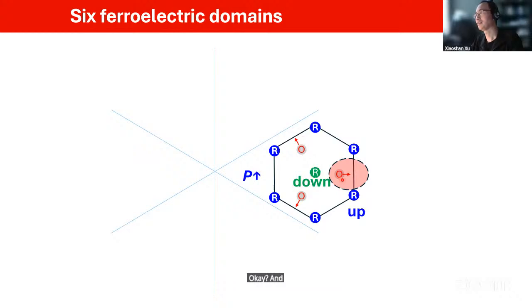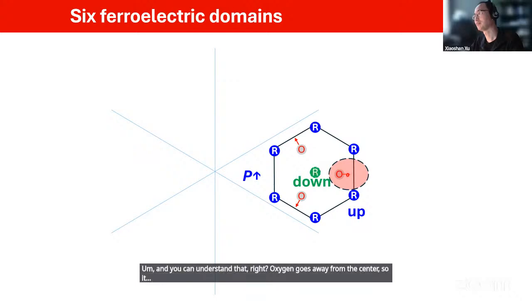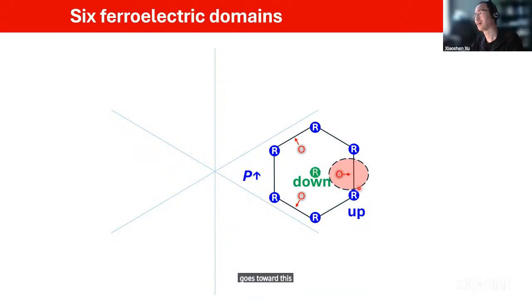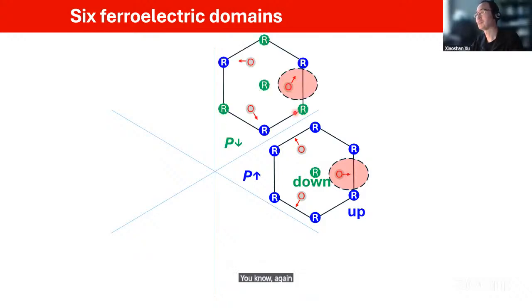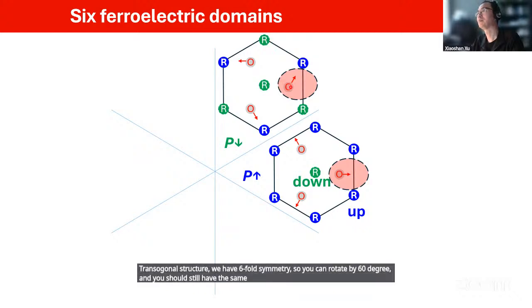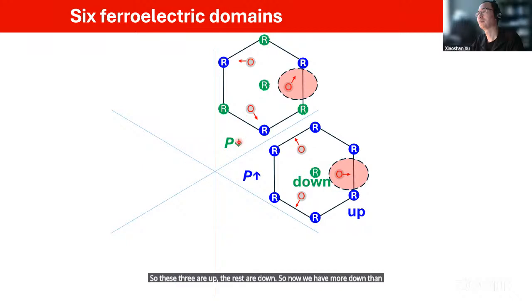And in this case, oxygen goes this way. And you can understand that, right? Oxygen goes away from the center, so it's dragged down. Oxygen goes toward this, so they are pushed up, okay? On the other hand, the oxygen does not have to go this way. Because the hexagonal structure has six-fold symmetry, you can rotate by 60 degrees and you should still have the same material. So in this case, it goes toward these three. These three are up, the rest are down. So now we have more down than up. So this is polarization down.